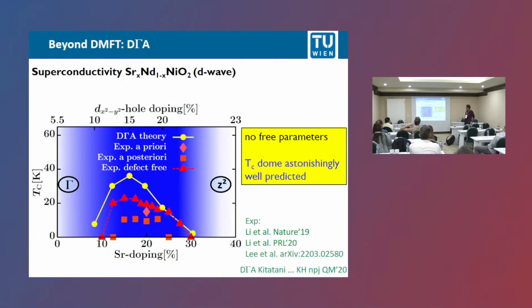And the difference to the cuprates is that the regime is larger, but it's only larger as a function of strontium doping. If you go to the doping of your x squared minus y squared orbital, you have something like 12 to 22%. That is similar to the cuprates. Then you also have a little bit of skewness in the superconducting dome compared to the cuprates, and that is because you have no linear scale in this doping regime. So all of that is nicely explained.